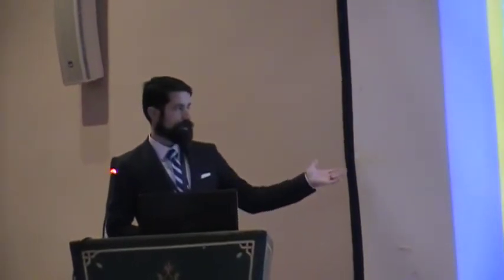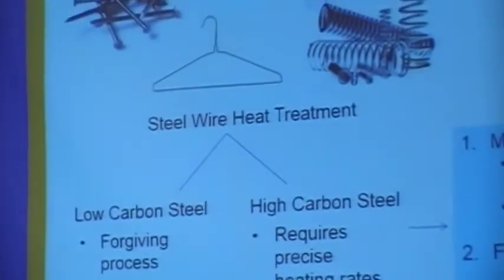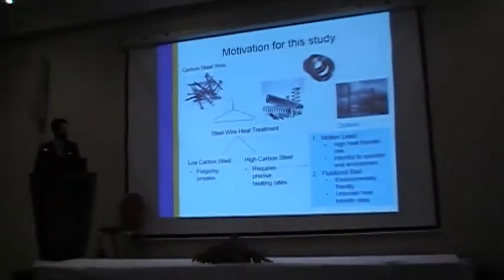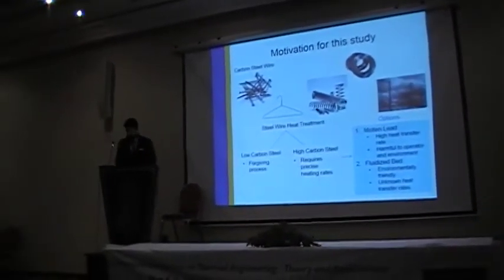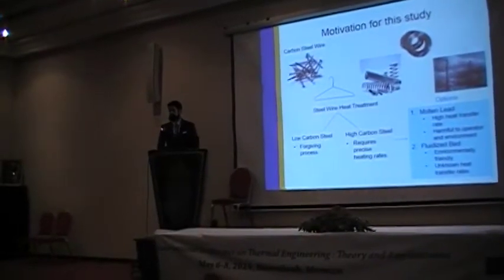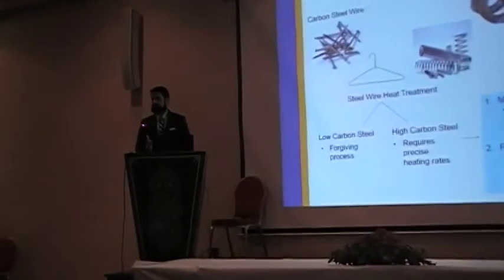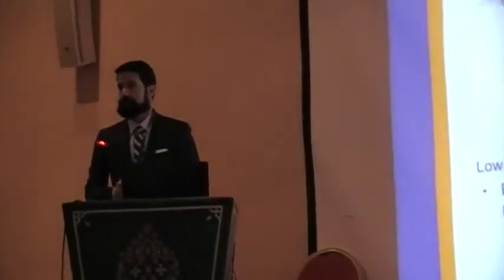So depending on the kind that you have, either low carbon steel or high carbon steel wire, the process is different. In the case of low carbon steel, it's a straightforward and fairly forgiving process, but high carbon steel requires very precise heating rates and stringent temperature controls. Typically, molten lead-based furnaces are used in this application. They offer very high heat transfer rates, however they're quite harmful to both the operator and environment. And for this purpose, they've been banned in many jurisdictions and require very expensive environmental controls to operate in others.